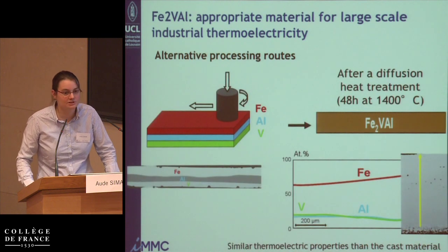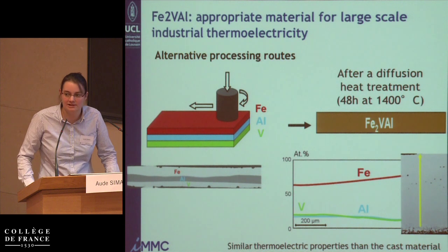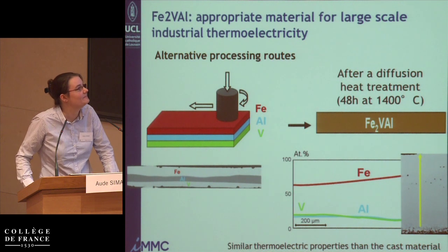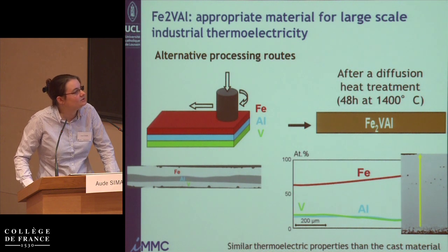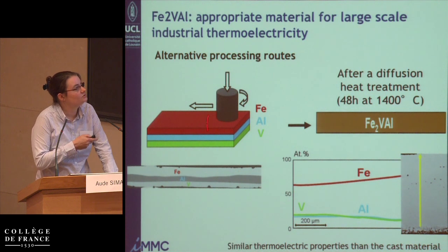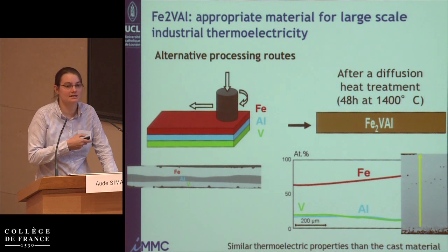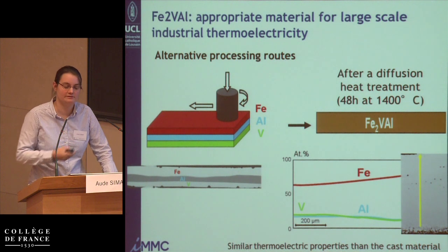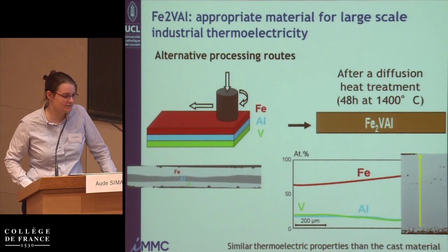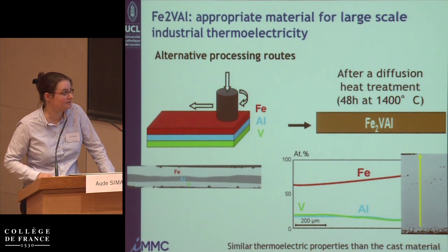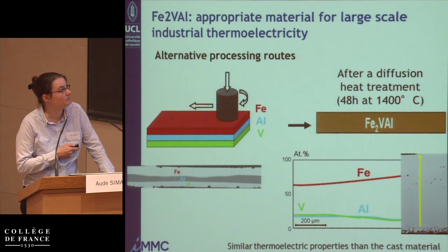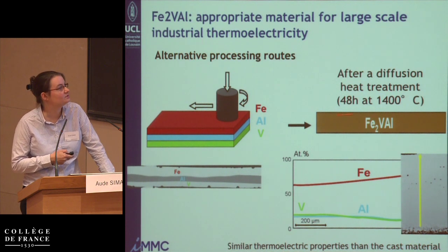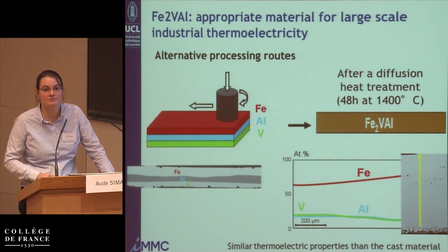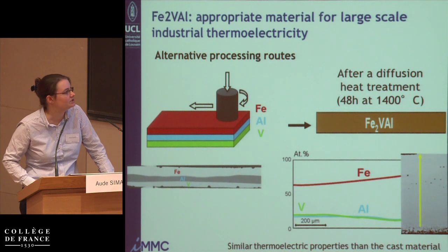So since I like friction stir processing, I thought, why not try to use friction stir processing here? And so what we did is use a tool that is not exactly a friction stir welding tool, but well, it's quite similar. It's made of tungsten carbide, and this process has been patented because it's also useful for welding iron and aluminum, which has a lot of other applications.